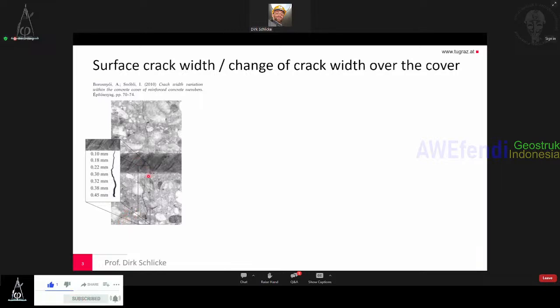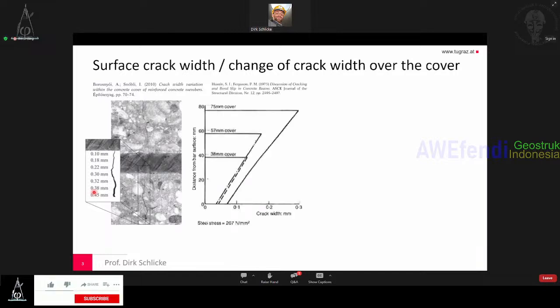But here you see also the crack width over the concrete cover. And we can see at the bar level, the crack width is very small, like 0.1 millimeter, and it grows significantly to the surface, up to 0.45 millimeter. As said, there's more than this one experiment. There's, for example, another one from Hussein and Ferguson, 1973, so also quite old. And they also made